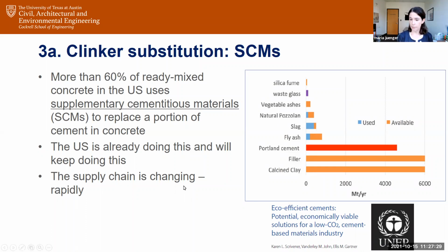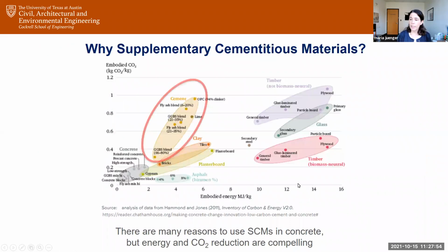When we're talking about supplementary cementitious materials, this particular chart on the right is an example of the types of materials we can use, and we do use. So Portland cement is on there as how much of this we use per year in million tons per year. And then we have other materials that are on this chart, such as fly ash, slag, natural pozzolans, calcined clay, etc. So we have a lot of different materials to choose from. The reason we're using these to replace a portion of our Portland cement clinker is because they inherently have lower embodied CO2. So this particular chart shows cement in terms of embodied CO2 on the y-axis and embodied energy on the x-axis. And so you can see where it falls here